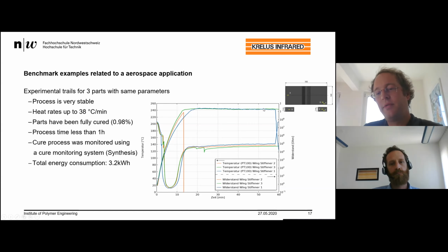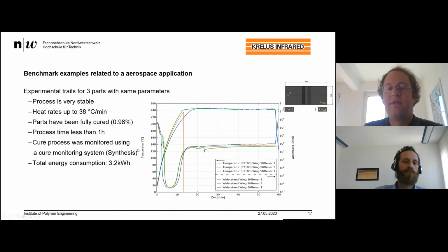So here on the right side, we are showing you 3 temperature curves from 3 different trials. So on the left side, you have the temperature, and on the right side, you have the resistance change in the part itself. So this is the system which we use to monitor the curing process. So, and as you can see, we can heat up everything really fast. So in less than 50 minutes, we are reaching a stable temperature above 240 degrees. And the system then reacts really fast.